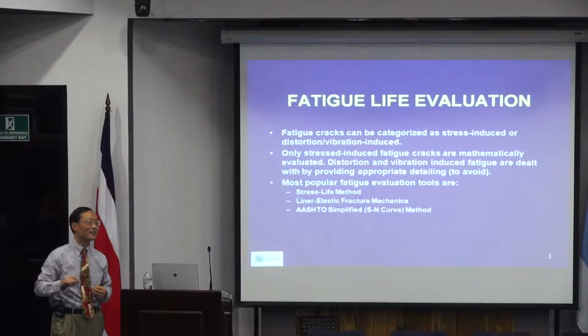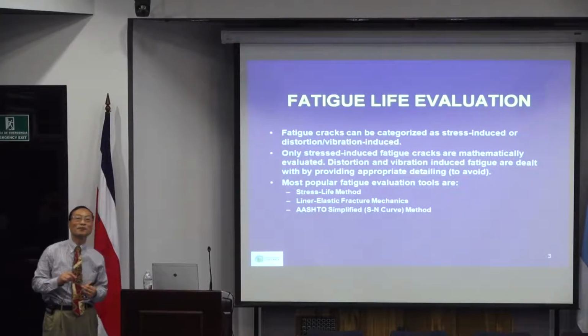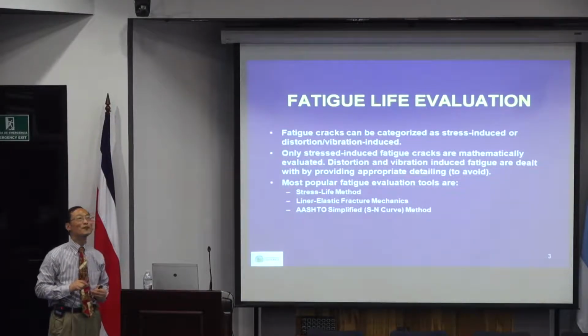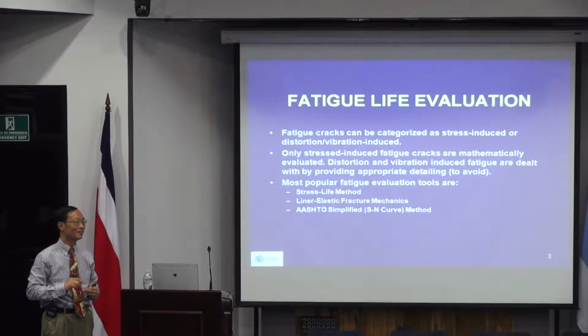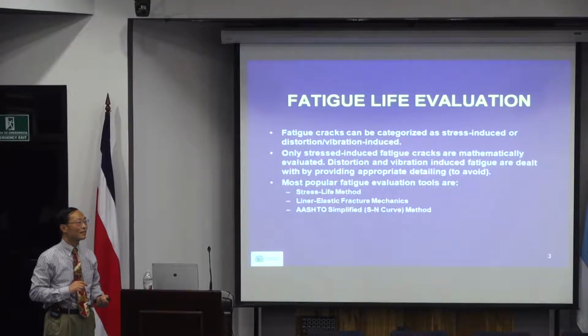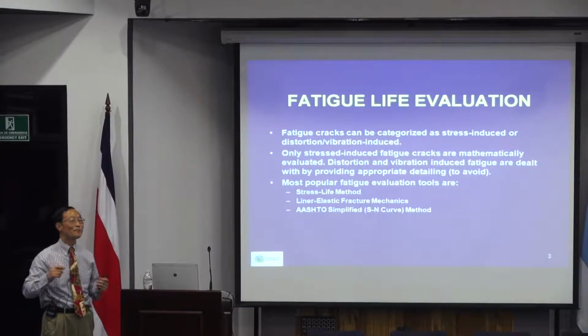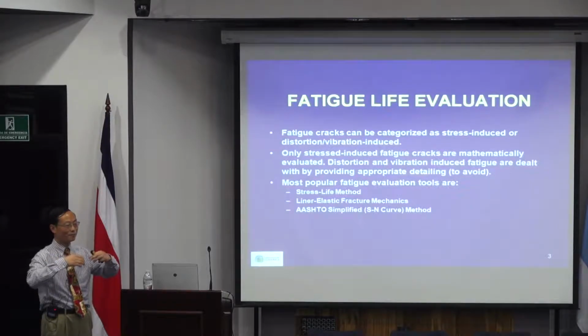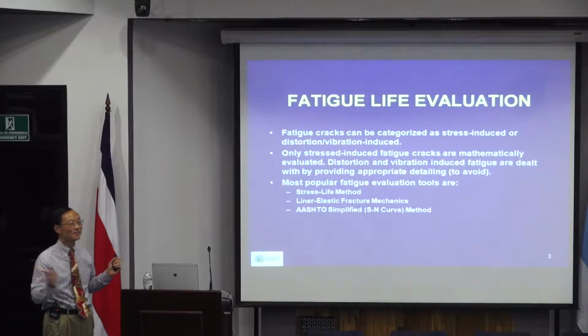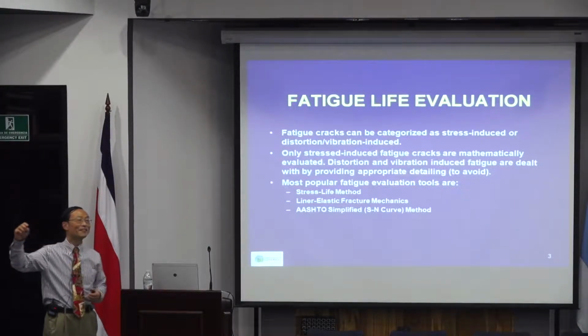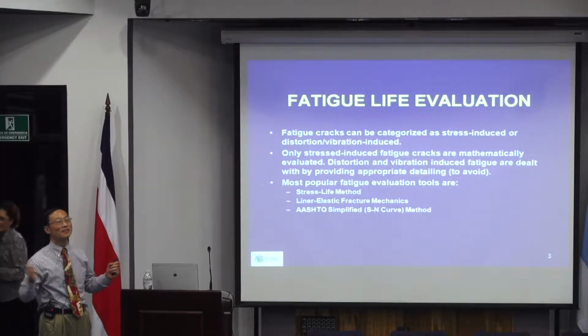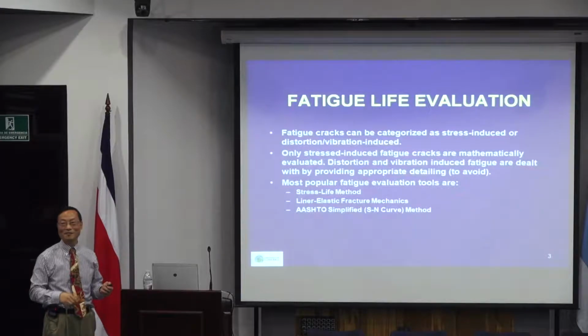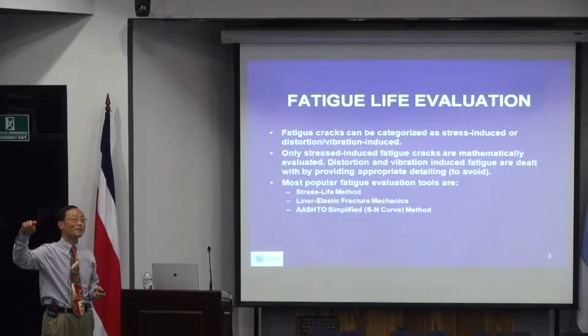That's typically done by mechanical engineers. But for structural engineers, like building or bridge structural engineers, we don't use that because it's too complex. So we did a lot of research, basically just testing. We apply a tension, release it, apply that large stress, and see how many cycles we can have, and then increase it. You get a lot of these dots, and once you have them, you can develop an SN curve.